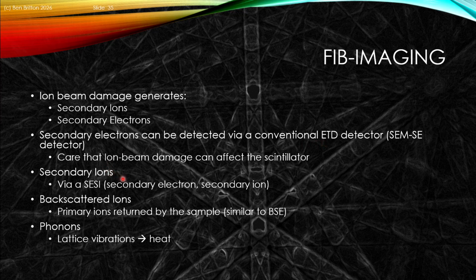You can also have secondary ions that are generated. Those secondary ions can be effectively collected through a secondary electron secondary ion, or SESI, detector. They can also be collected through a few different cases, and those secondary ions can also be collected, for instance, through a secondary ion mass spectrometry, or SIMS, system. You can have backscatter ions, and so those primary ions are returned back by the sample. That's similar to, say, BSE type imaging. And you'll also get the formation of phonons in the material. These are quantized lattice vibrations, and that will create localized heating in the sample. And we'll see in certain cases that localized heating needs to be managed with care.